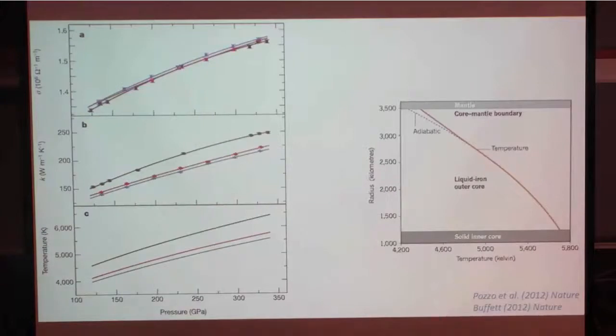The core: there's a new twist to our understanding of the core, which has come from new ab initio calculations of the thermal conductivity of iron at core conditions, and also some subsequent experimental measurements, one set of which agrees very nicely with this prediction, and another set which disagrees completely. But anyway, if the thermal conductivity in the core is really this high, much higher than we thought before, then our picture of the dynamics of the outer core might be very, very different.